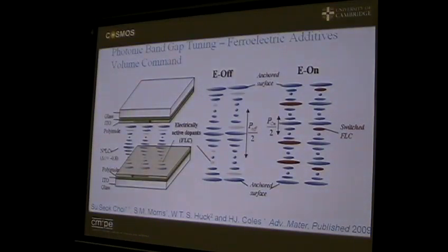And so you can take your chiral nematic material, and you've twisted it, and then you switch the surface an extra quarter turn, which tightens the helix, or you go the other way. So you actually use the surface where my hands are to twist through 90 degrees in opposite directions, and you make for a tighter helix. And that gives you a facile tuning method.